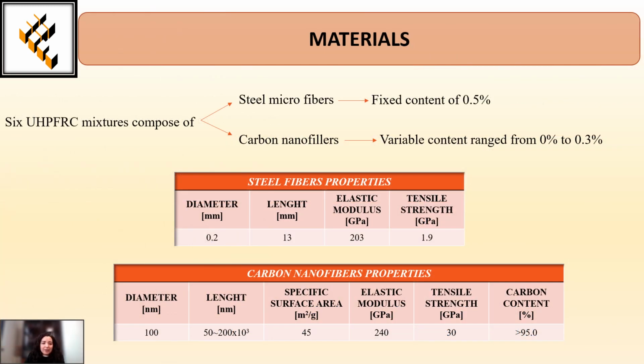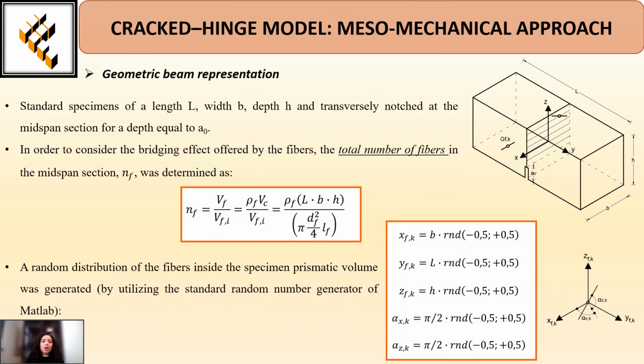As regards the material, six mixtures composed of steel microfibers with a fixed content of 0.5% and carbon nanofillers with a variable content ranging from 0 to 0.3% were considered. For the geometric beam representation, a standard specimen transversely notched at the mid-span section was considered.